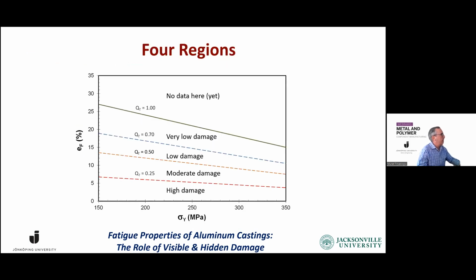When we look at the overall regions, above 1.0 we don't have any data yet. I think with more time there will be more data there, so the maximum trend line will shift, but for now we will use it. Between 0 and 0.25, we have a highly damaged area, and most of our castings reside in that area. I would say 90 to 95% of our castings are highly damaged. 0.25 to 0.5 is moderate damage. 0.5 to 0.7 is low damage, and then 0.7 to 1 is very low damage.